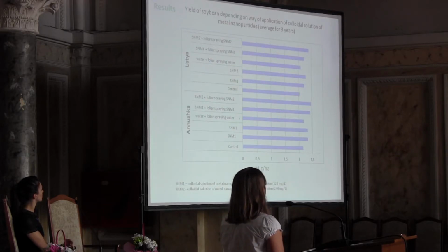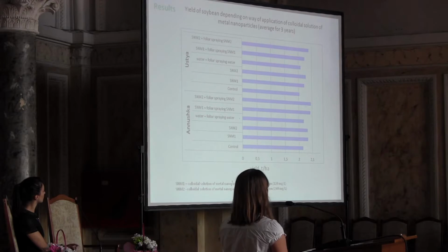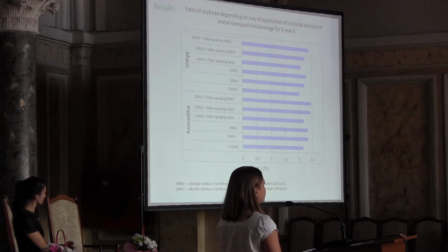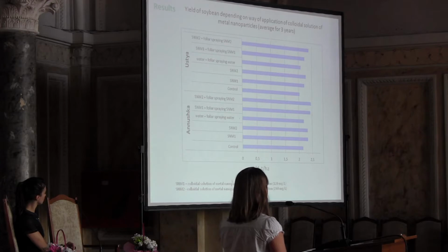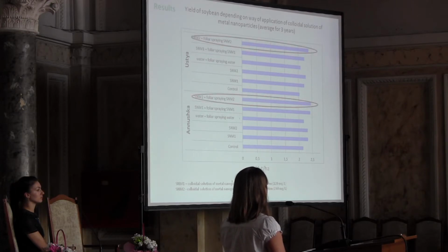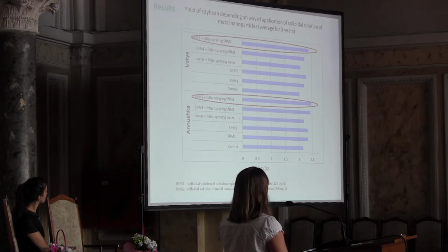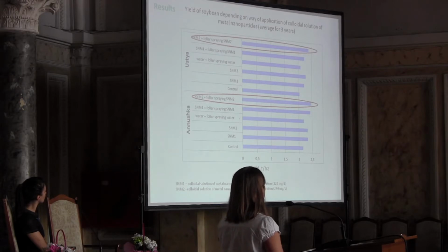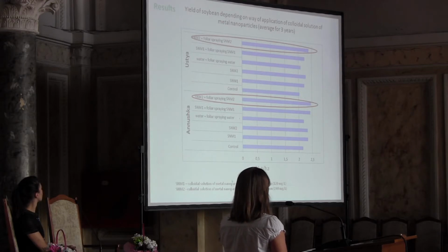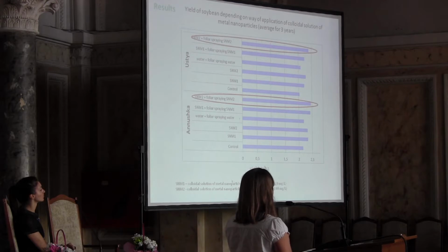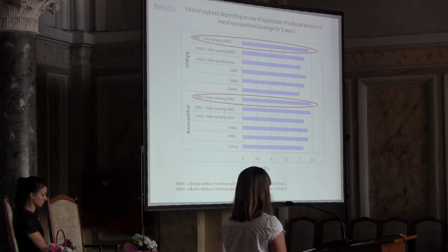Yield of soybean depended on the way of application of colloidal solution of metal nanoparticles for both cultivars, and the highest productivity was obtained after the double treatment with colloidal solution of metal nanoparticles. It was pre-sowing treatment and foliar spray in flowering phase. And the highest yield was at the level of 2.4 and 2.39 tons per hectare.